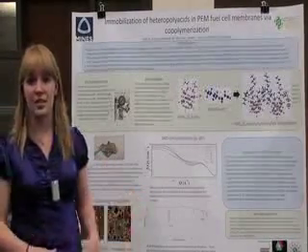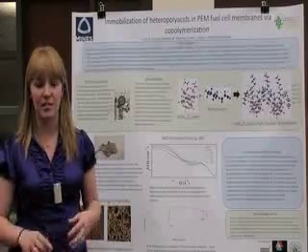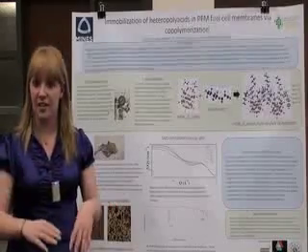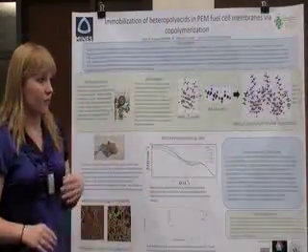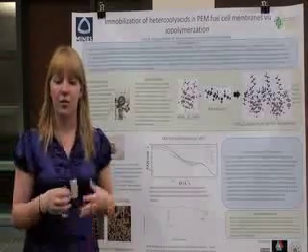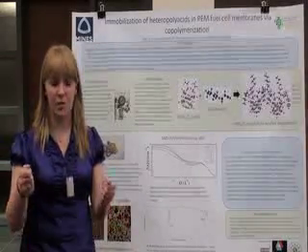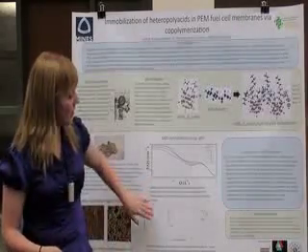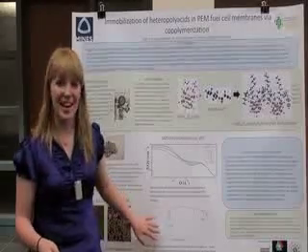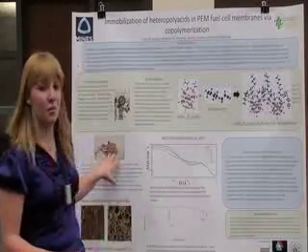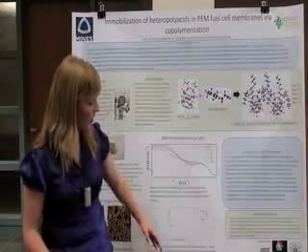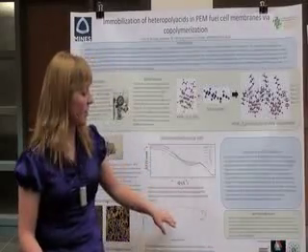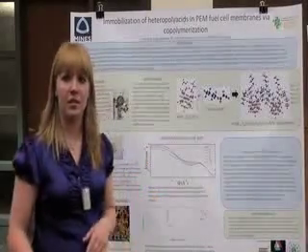There's a lot of problems with this system so far. It's not homogeneous, so it's very phase separated and it doesn't give good proton conduction. And also, it's very thick, which isn't really feasible for a fuel cell membrane. So there's much work to be done on that. But here's an IR spectra that I did of this comonomer, and it shows that there's a carbon-hydrogen and a carbon-carbon bond and the heteropolyacid. But the benefit of this is that it shows that there aren't carbon-carbon double bonds.